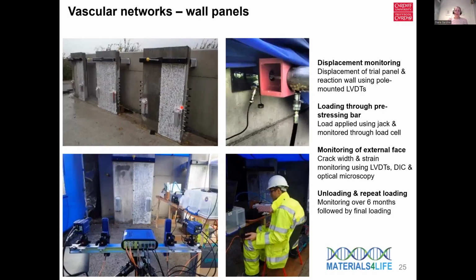We unloaded and repeatedly loaded those walls over a period of 6 months and then had a look at the final results. And this is just an image to show the panels in situ. Panel B, which is this panel over here on the left-hand side, had the vascular networks with sodium silicate in them and also had a series of shape memory polymer tendons in accompaniment. There were vascular networks in a series of other panels, these control panels, but they were left empty and just used as our control case.